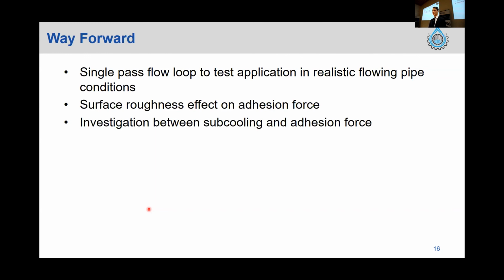So historically with a lot of these materials we've seen, and also with hydrate particle cohesion, that a decrease in subcooling results in an increase in adhesion force because that liquid layer around the particle melts a bit more and contributes to that adhesion. And basically, I just think this will contribute to the understanding and profile of that material more if it was potentially to progress to industry.